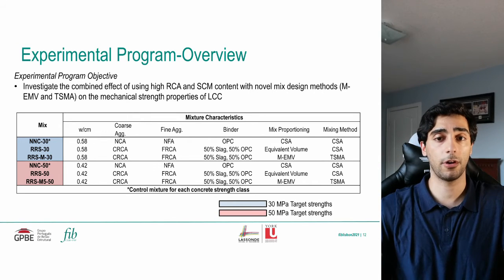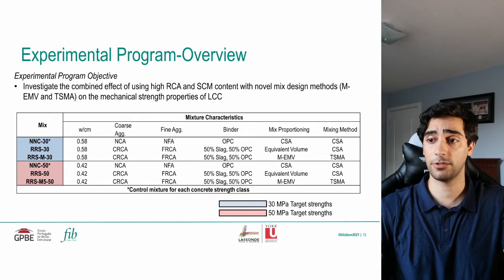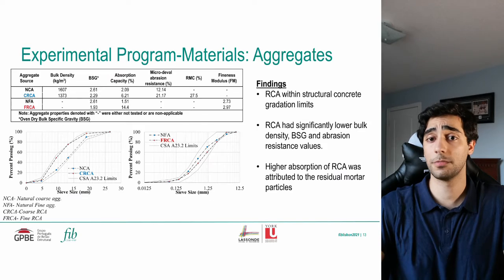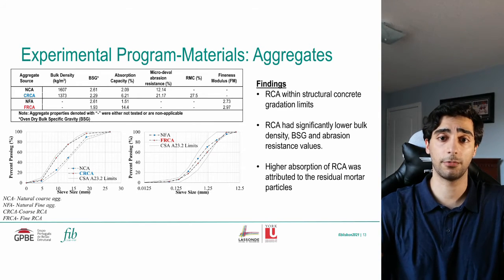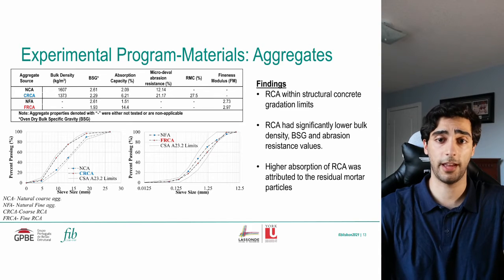Now, our mix design program was split into two separate sections consisting of a low and high strength mix with a target strength of 30 MPa and a target strength of 50 MPa. The mixture characteristics of the two mixtures are shown in the table provided. In terms of the material properties, starting with the aggregates, it was found that while the RCAs were produced in a different manner compared to the natural aggregates, the RCA were able to meet the structural concrete gradation limits.